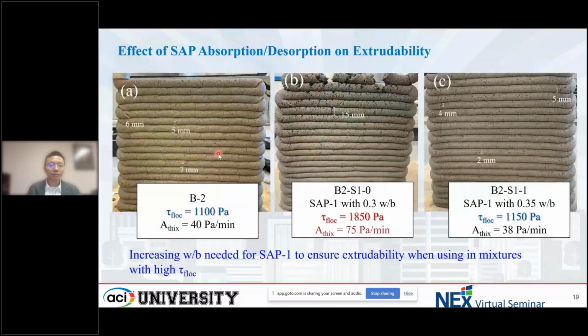And this is the effect of SAP1 on binder 2. For this one, because it increased the floc value to a very high level, we can see significant tears on the surface, and the tears happen completely across the cross section. We cannot continuously print the structure. And also, when we increase the water binder ratio, it becomes better, with similar properties to the reference mixture. So we make a conclusion that increasing the water binder ratio is needed when you use SAP1 in order to ensure a good printability.